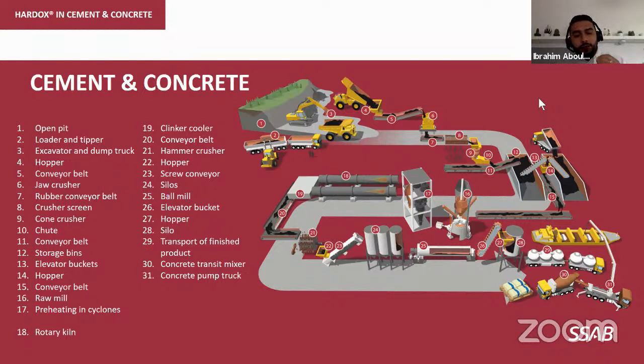But up to 600 degrees, we have developed a product called Hardox HiTemp, which can withstand temperature without back tempering up to 600 degrees. Then we move forward to step number 20, in which we have conveyor belts and hammer crushers, which can be relined with Hardox grades from 500 to 600, or sometimes even Hardox HiTemp. In some cases, when the hammer crusher is crushing the clinker coming out, it's still a little bit hot, around 300 to 350 degrees. In that case, relining with Hardox HiTemp will extend the service life of your liners.